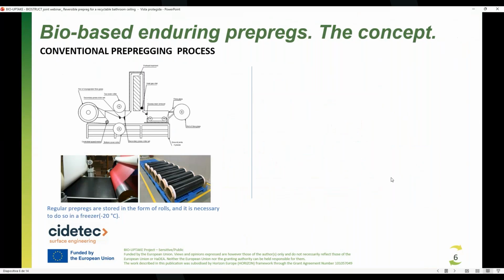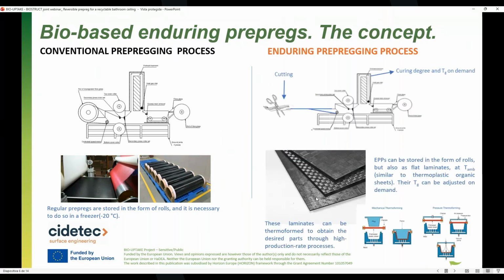Using this kind of resin in the manufacturing of prepreg materials gives an advantage, and that is that the prepregs can be made like what we call enduring prepregs. So a regular prepreg is usually stored in the form of rolls, and it's necessary to do it in the freezer because they need to be kept in a tacky stage to be used afterwards. But when we have enduring prepregs, the manufacturing process, as we saw, is the same, but in addition to being stored as rolls, they can also be stored as flat laminates, as we can do with thermoplastic organosheets.